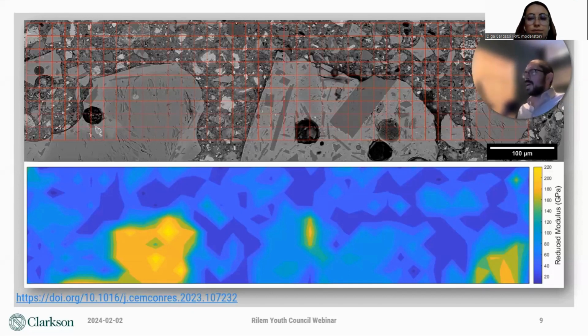You can see here that the aggregate particles are quite hard, while the hydrated cement paste that binds them together is quite a bit softer. Interestingly, we find that the micromechanical properties don't change very much at reduced gravity, which tells us that the dominating effect of microgravity is actually on the consolidation of the fresh concrete and the resulting impacts on the air void structure. This is important because once we understand the mechanism at play, we can theoretically design solutions to overcome that effect.